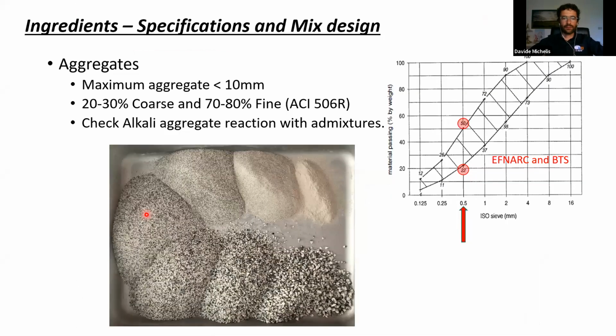Aggregates. In terms of weight, it's the most important component. It's necessary to keep the aggregate size lower than 10 millimeters, because if we exceed this size, there could be a big rebound. So you lose money and you lose material when you apply the shotcrete. And it's absolutely necessary to check before use the alkali aggregate reaction with the admixtures used inside the mix design, in order to avoid this phenomenon that is really risky and damaging for the structure.